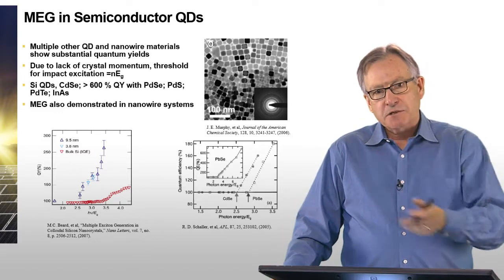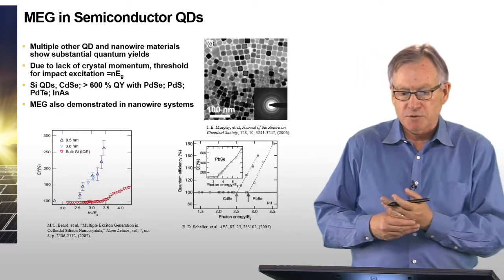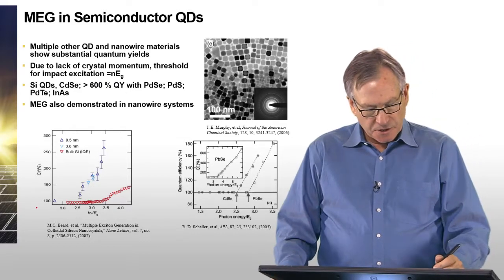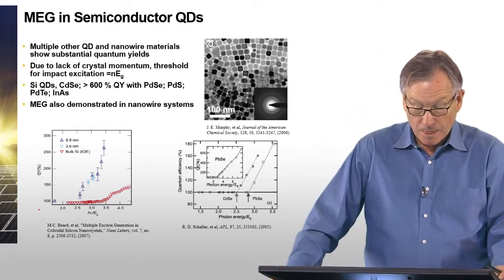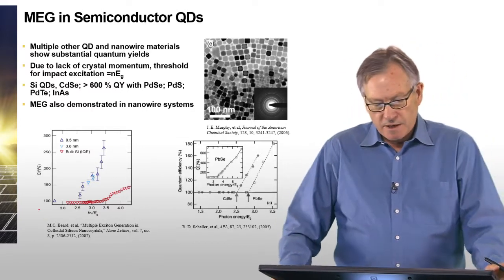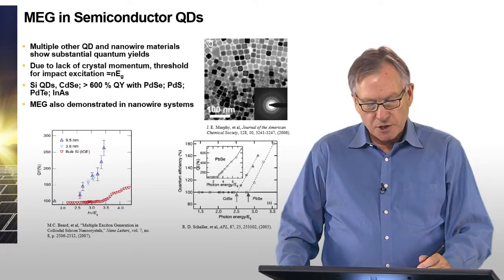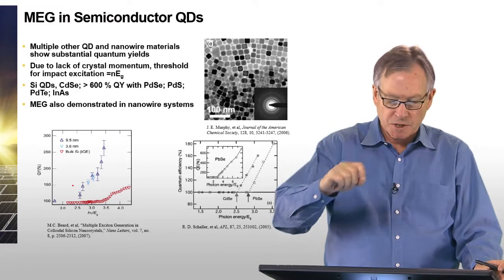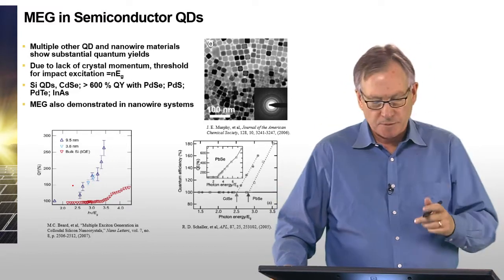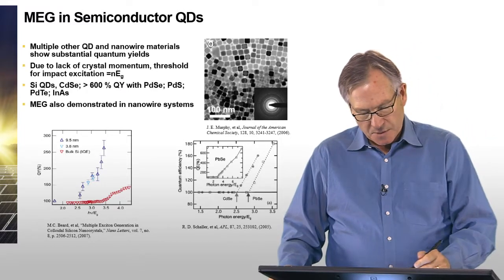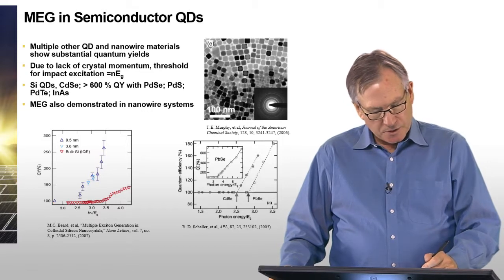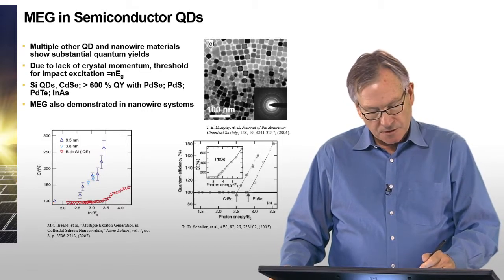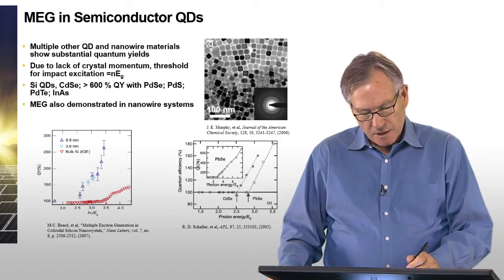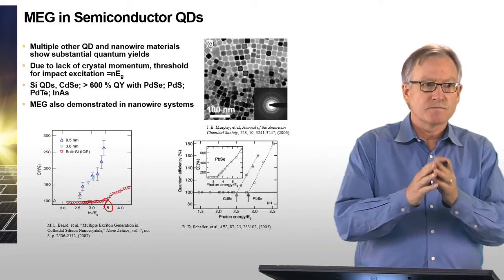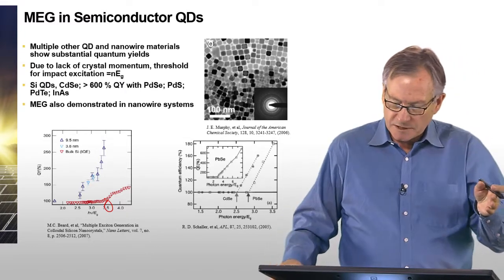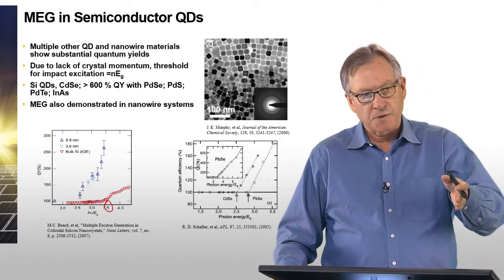As I mentioned, practically speaking, in bulk silicon this isn't feasible; we don't get a strong effect. And that's illustrated in this picture down below. This is research work from Matt Beard's group at NREL. It's a comparison of the quantum yield, which is the number of electron hole pairs created per photon, measured optically. So this is an all optical experiment. This is basically bulk silicon. And as I mentioned, instead of having a threshold at twice the band gap of silicon, there's no multiplication effect until you get above about 3.5 electron volts, which is basically at the end of the UV portion of the solar spectrum.